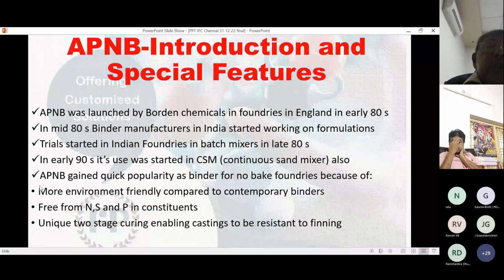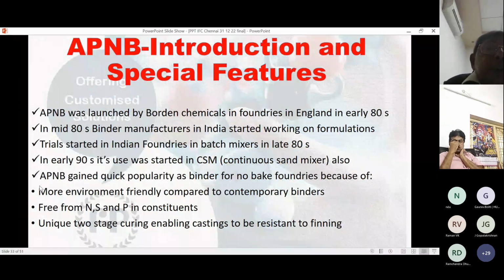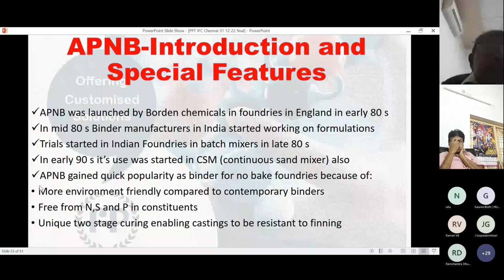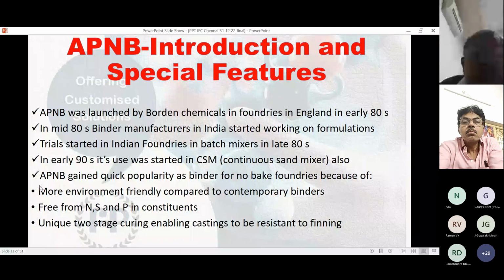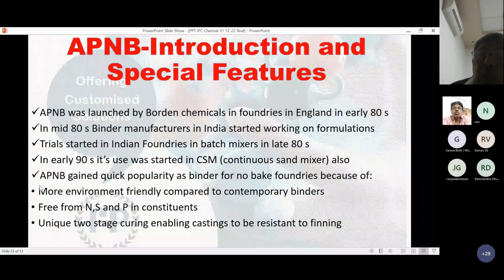It was introduced in Indian foundries and world foundries at a later stage, in the middle of the 80s, but this system got quick acceptance in Indian foundries. By the 90s, it got recognition as the binder for continuous sand mixers. The reasons for its quick popularity were: more environment friendly compared to contemporary binders, free from nitrogen, sulfur, and phosphorus, leading to metallurgically sound castings, and a unique two-stage curing that enables castings to be resistant to finning.